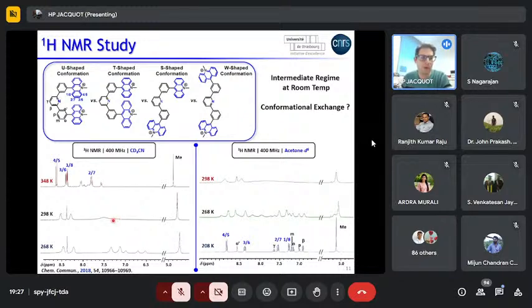To confirm this, what we've done is heat up the solution, and indeed we have a simplification of the spectrum. And at low temperature, we have to change solvent from acetonitrile to acetone. At low temperature, we have a new proton NMR, and obviously, we have a very symmetrical molecule. We have only one set of signals for each proton. So this means that eventually we have one conformer in solution.